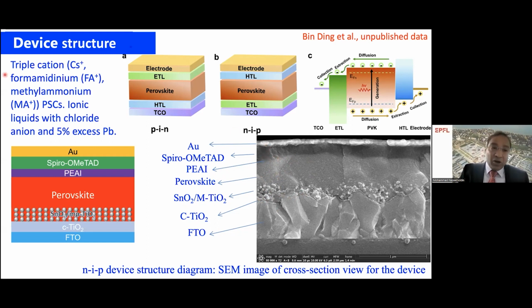Now, if you look at our compositions, in all of them invariably we have a 5 to 10% excess of lead iodide. Why are we using excess lead iodide? When we use this type of larger cations, this excess lead iodide forms a thin layer of two-dimensional perovskite. That two-dimensional perovskite layer passivates interfaces and reduces defects. You will see more details in coming slides. So this is the typical architecture of our devices, NIP and PIN. The cross-section image and the composition are shown here.